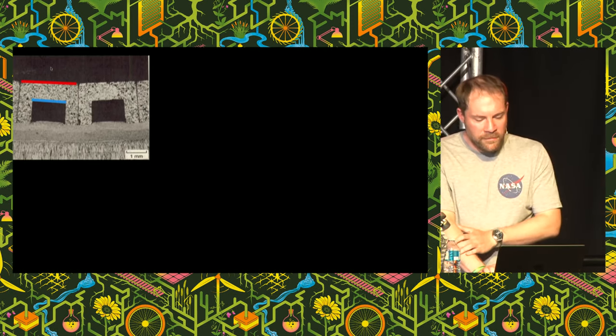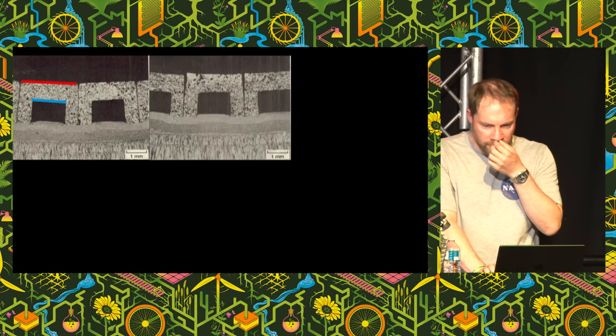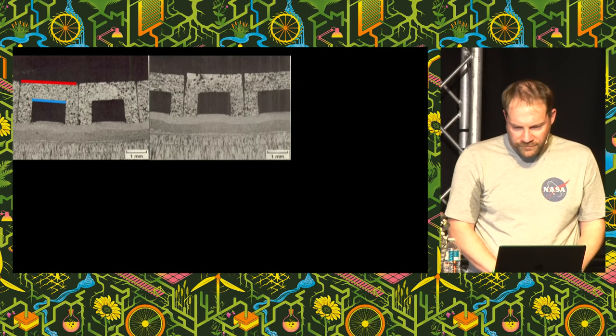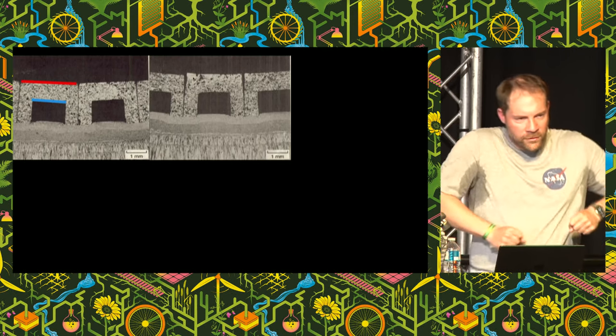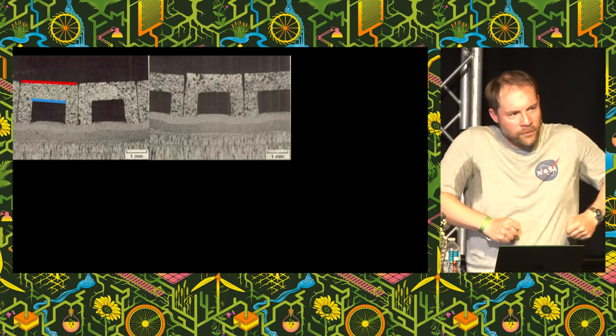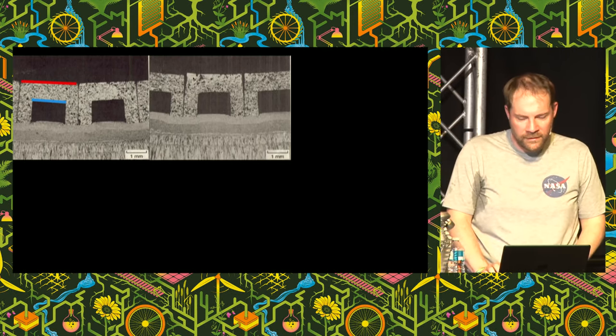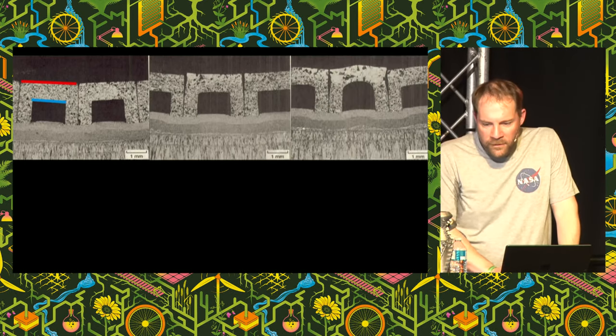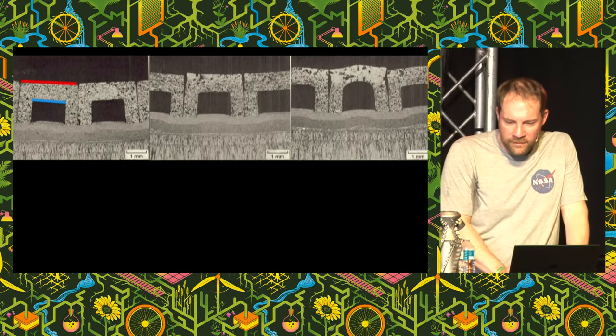So this is a picture from before they fired it, and then after a few firings, you can see that the shoulders are starting to plastically deform from rubbing up against each other and get a bit out of shape. A few more firings, you can see this thermal strain is starting to bow the wall out.